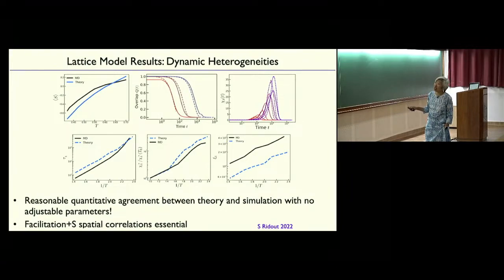You know, not perfect, but again, not bad. The relaxation time, okay? The height of the peak, chi4, a little bit off, okay? The thing that's the most off, but has the right temperature dependence, is the correlation length of the kinetic heterogeneity, okay? The 4-point correlation length, okay? This thing increases for both of them with about the same temperature dependence, but it's off. If you wanted to use numerology, it's off by a factor of about 4.